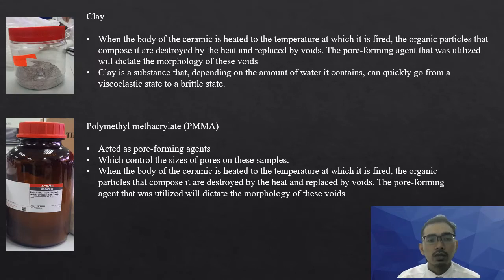Okay, the next material is clay. When the body of the ceramic is heated to the temperature at which it is fired, the organic particles that compose it are destroyed by the heat and replaced by voids. The pore-forming agent that was utilized will dictate the morphology of these voids. Clay is a substance that, depending on the amount of water it contains, can quickly go from a viscoelastic state to a brittle state.